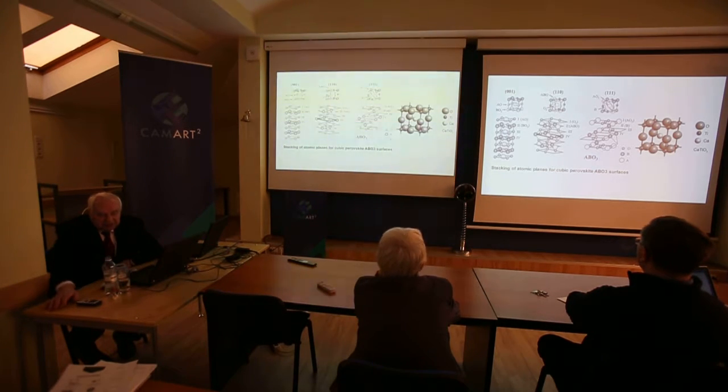You see that in perovskites, calcium and strontium and others are practically ionic. Calcium 2 plus, strontium 2 plus, and in calculations, Dima, when you made calculations, you calculated the charge on this A atom close to 2, something like plus 1.8. But the bonding between titanium and oxygen is essentially covalent due to the electrons of titanium.